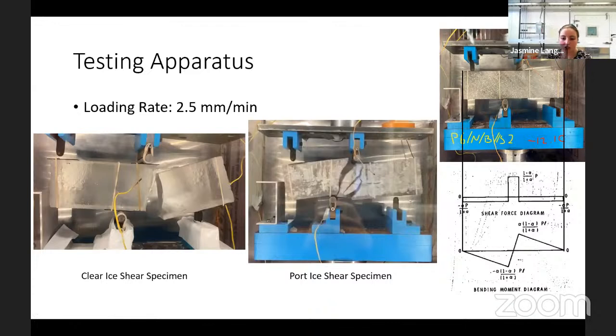The 2 left pictures show some of the failures. The middle one shows the port ice specimen failure, and most of them looked like that. They would break in the middle, either into 2 pieces or 3 pieces, but 3 pieces was more common. The left one shows one of the shear specimens, and this one broke outside of the 2 bars, which we didn't see very much of. It was cool with the clear ones because we could actually see it cracking while it was going, versus the port ice, where you could not tell that at all because of all the sediment. And our loading rate was 2.5 millimeters per minute.